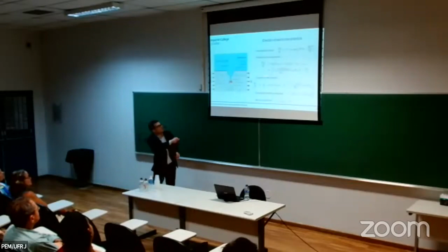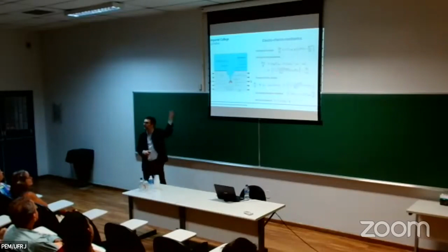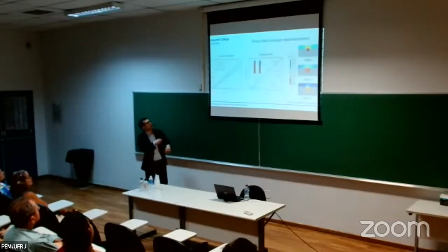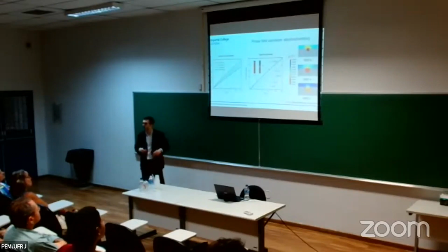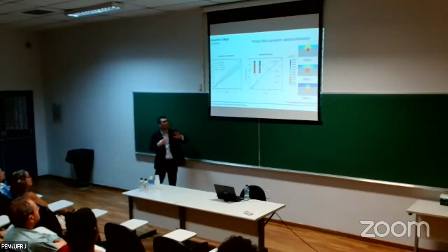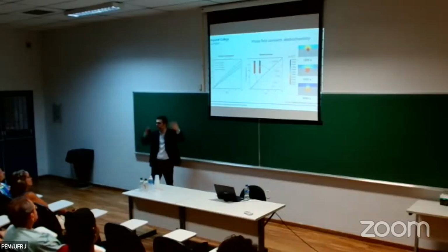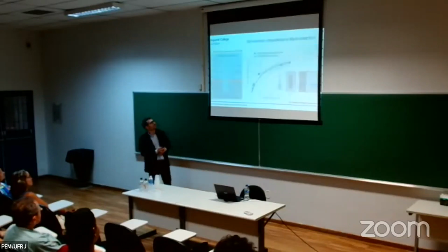So here we can solve for as many reactions and ionic species as we want, similar to what we did in the beginning with hydrogen, and we can capture the role of the solvent concentration, of the pH potential, and so on and so forth. So as the pits and the cracks propagate, you can capture how the environment is naturally evolving as a result of this corrosion process. So a lot of things are happening, but all of those things can be simulated with this framework, provided your computer is large enough.